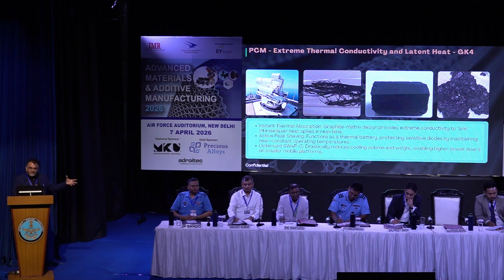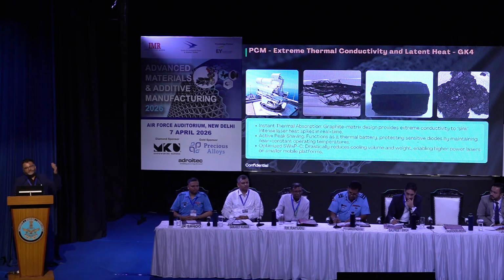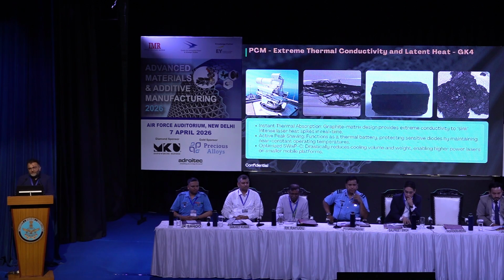Now when we observe the Helios, which the US is using, they are using paraffin wax based phase change materials. We studied exactly what is required, and we need two critical things which don't go together: high thermal conductivity and high latent heat. You don't have those solutions. With multi-wall carbon nanotubes and a few more chemicals, you can make extremely high thermal conductivity, which can go up to 200, 300 with very careful nanoparticle engineering and paraffin wax like hexadecane. You can solve this. We developed the solution and offered it to defense, that we can reduce the size of laser weapons and mount them on aircraft, drones or ships.